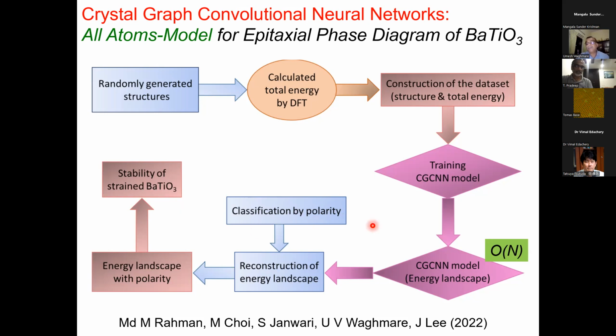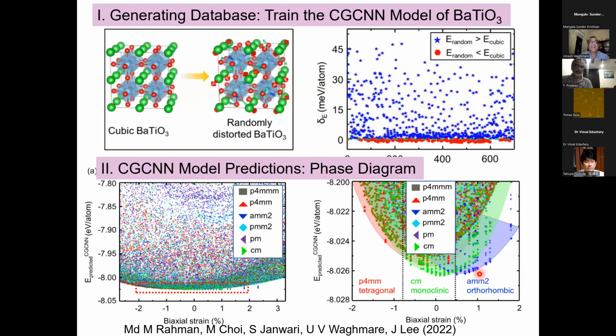And this is very efficient because the computational scaling of this approach is order n, which opens up lots of possibilities. And then we applied this approach for epitaxial barium titanate films, and we reproduce sort of experimentally seen phase transitions from tetragonal to orthorhombic phases. So this is sort of the new development we are involved in, basically using machine learning to predict phase transition behavior, but by basically modeling DFT energies.